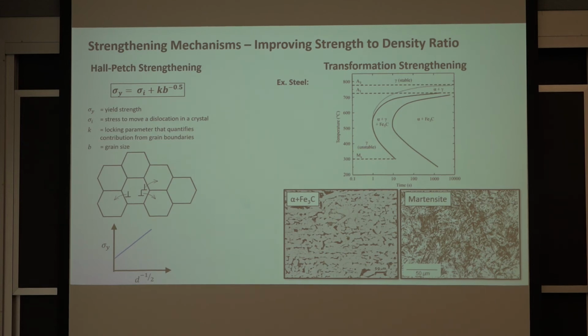The martensite, as you can see from these micrographs, is a much finer microstructure, made up of tiny nanoscopic platelets that stick together. That's similar in concept to having smaller grains, and that's why martensite is so much stronger than, say, a ferrite material. Martensite is much more capable of tangling up and trapping dislocations because of its microstructure than the ferrite was. So here's a case where you've changed the structure of the material to form something stronger than what you started with. This is transformation strengthening.